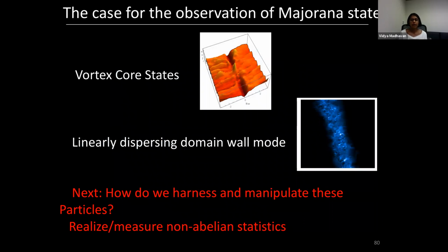There are many different ways to get Majorana fermions. You can have a topological superconductor. You can do something quite clever by using nanowires with spin-orbit coupling, put them on a superconductor and so on. And you can also, if you're lucky, find materials where you have superconductivity and topology all in one material. And if you do find such a material, then you can go looking for Majorana fermions, either in the vortex cores or in phase-shifted regions. And there's a lot of indication that FeSeTe might be one such material. And certainly all the experiments that have been done so far seem to support that.